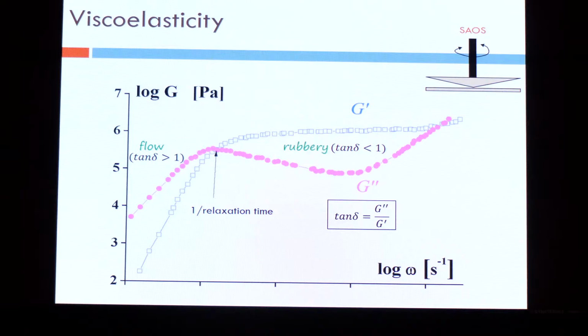The material is the same, but depending on how you measure it, you get a viscous response or an elastic response. And there is one particular property that I will come back to during the talk, which is the ratio of these two. It's called the tangent delta. It's simply the ratio of the viscous part to the elastic part as is shown there.